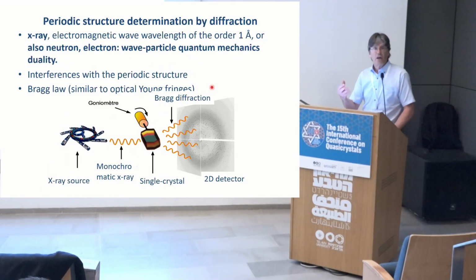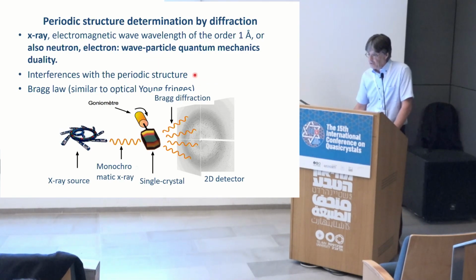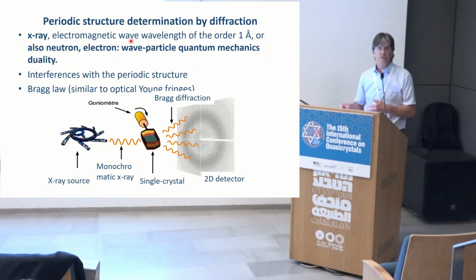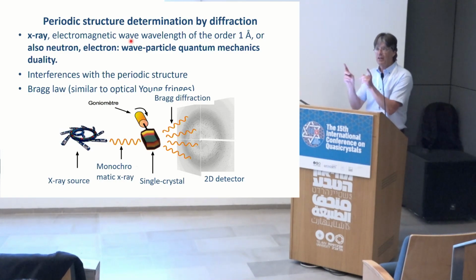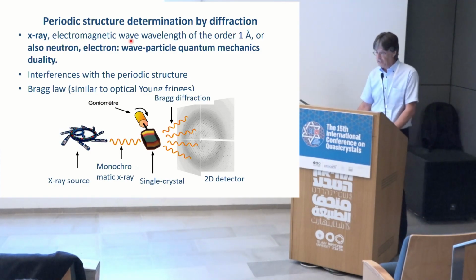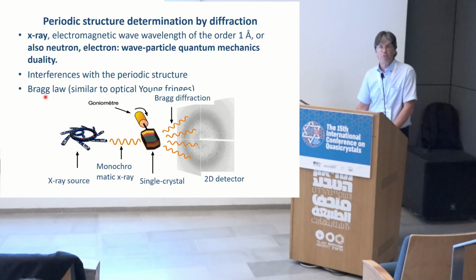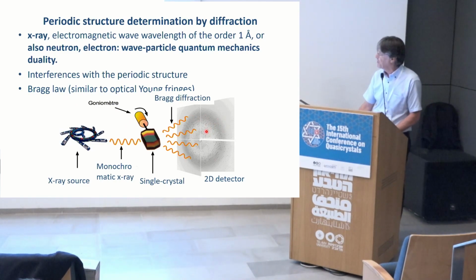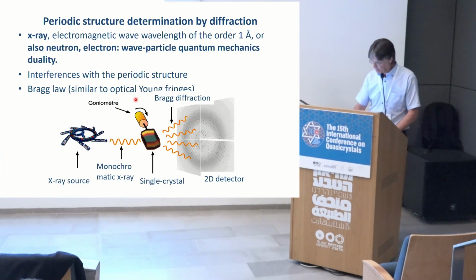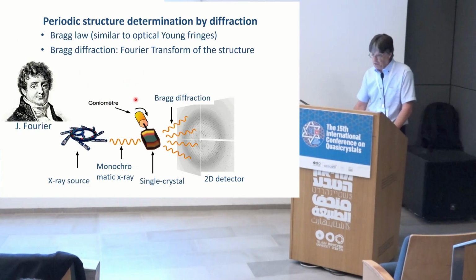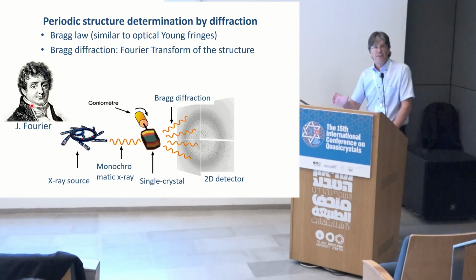And if we want to solve a structure using this periodic arrangement of atoms, there is a method that was discovered more than 100 years ago: you can use X-rays or neutrons, or electrons, with a wavelength which is of the order of the interatomic spacing. And because we have periodicity, we have constructive and destructive interferences, and we have what we call Bragg peaks, which are the sharp spots that you're seeing here, exactly the same as what you would observe with optical Young fringes.